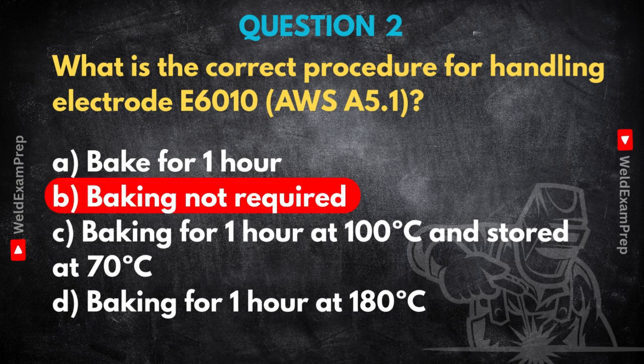Not required. Why is that? I thought most rods needed baking. Well, many do, especially low hydrogen types, but E6010s are different. They're cellulosic electrodes. Their coating is designed to have moisture, which produces hydrogen in the arc. Hydrogen? Isn't that usually bad? Causes cracking. In many cases, yes. But for cellulosic rods like the E6010, that hydrogen is actually beneficial. It gives it that forceful digging arc and deep penetration they're known for. Baking them would actually drive off that necessary moisture and degrade their performance. You'd lose the very characteristics that make them useful.